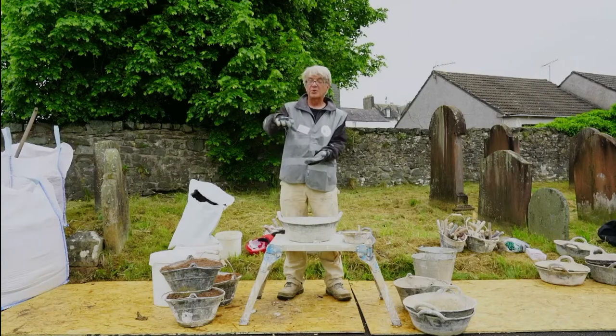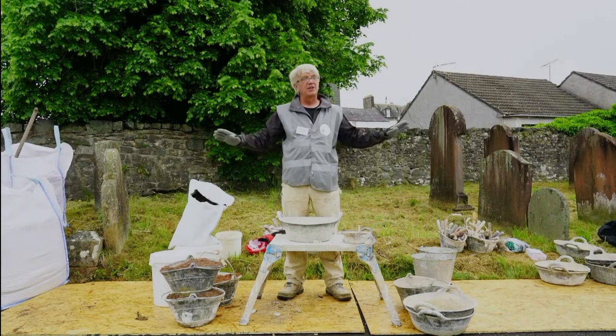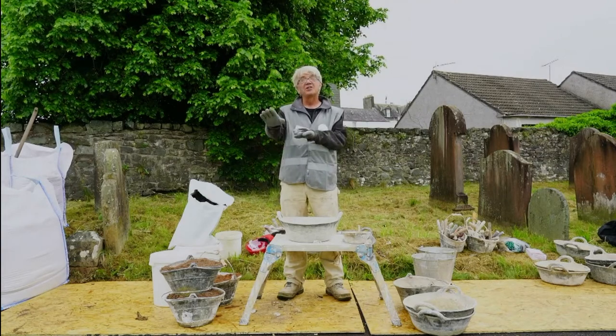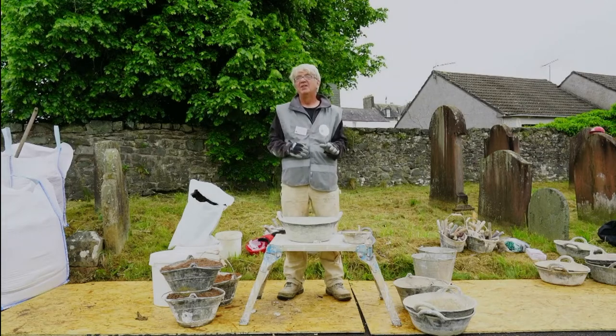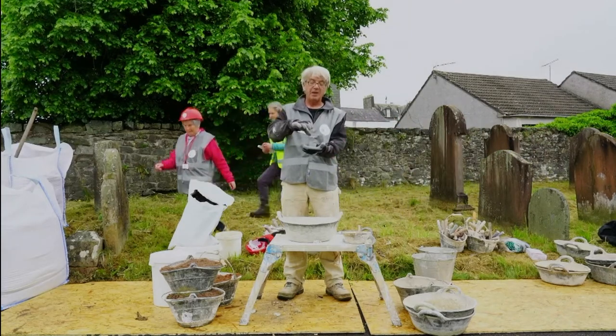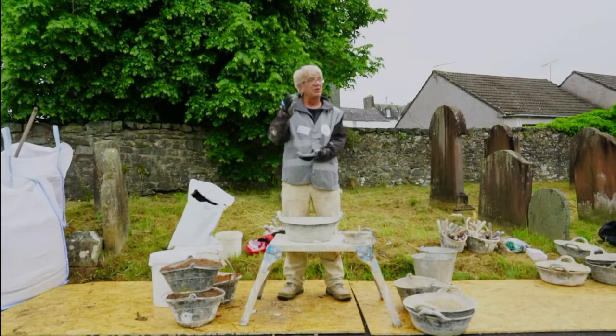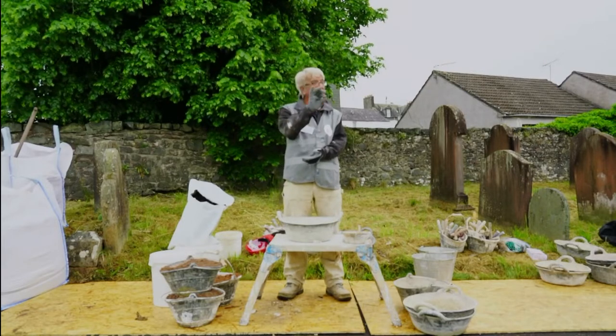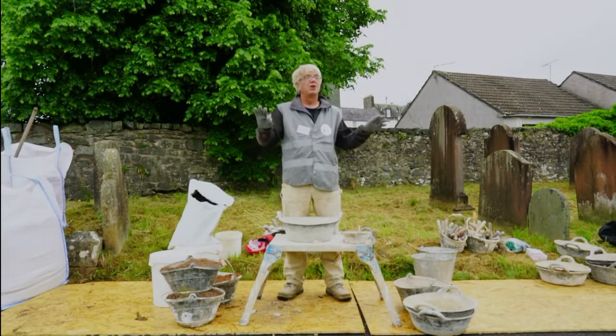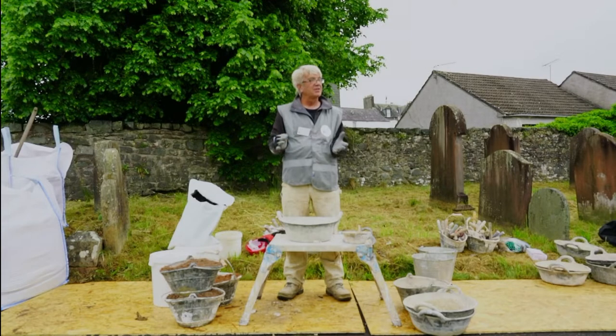If you put a porous brick to a cement sand mortar, which has no water retentivity to speak of, it wants to dry as fast as it possibly can. And because that's a hydraulic material, it needs water to set. Airlime doesn't need water to set. It needs to get rid of water to set and replace it with carbon dioxide. Then you bed a brick to that. The water in the mortar, the contact zone, is immediately extracted into the porous brick or stone. That water doesn't come back. It doesn't set properly. And we're not talking visible things here. We're talking microscopic. But that will leave a capillary pathway between the mortar and the brick, if it hasn't set properly.